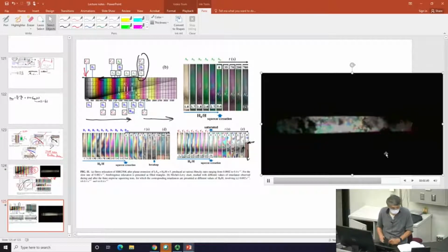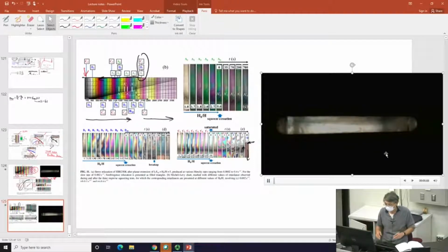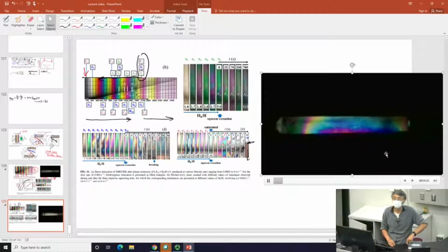So I think this was just an interesting update on the idea that a large amount of step strain is bound to produce force imbalance that produces disentanglement, and the disentanglement is a horse race, and it allows different parts to relax different amounts as a result of this.